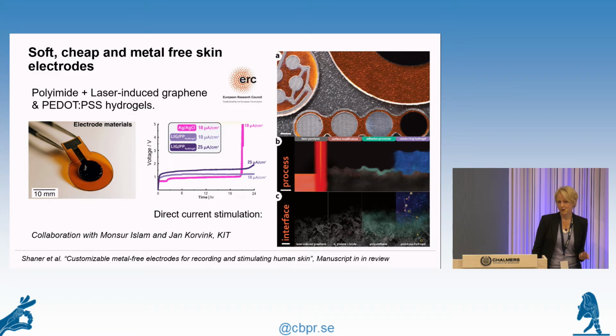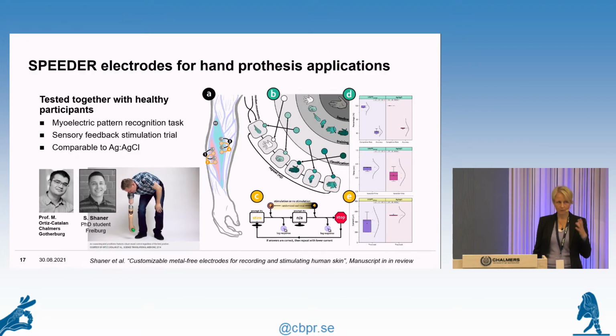So we have tested these devices a lot for direct current stimulation, which we want to use them for the wound healing assays. But we have also been fortunate enough to connect with Max, and also just as preliminary tests, see how well these electrodes compare to the industry standard of silver chloride for skin electrodes. And I don't know if Max agrees, but I think it's an extremely positive result that even with the first attempt, where we didn't optimize the device at all, so we just made a few test samples, the device is still rather thick, it's not really conforming to the skin, but it still performed almost comparable to silver chloride, both in the bioelectronic pattern recognition and the sensory feedback stimulation trial. So we were quite optimistic that we really could push this further by optimizing these materials for these applications.